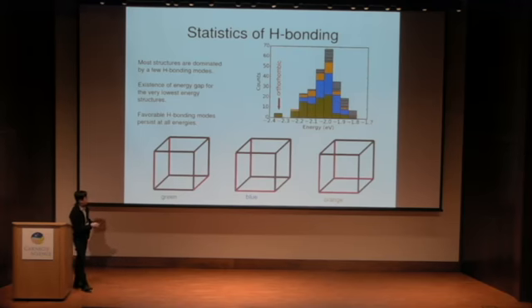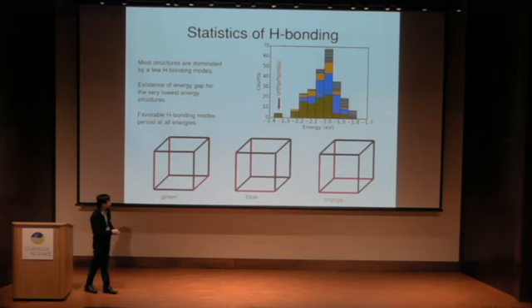Now, if you look at the very low energy structures, it turns out that all the hydrogen bonding modes in that structure have only one type, and it's this type. And actually, this corresponds to the orthorhombic phase. So all these structures in here are in the orthorhombic phase, and there's an energy gap between the structures here and those in the higher energy manifold. One thing I would like to point out is that even though this particular type of bonding mode is completely dominant at the lower energies, it continues to be very favorable even at the higher energies. So if I want to make a model from this kind of data, it makes sense to include this particular type of bonding.